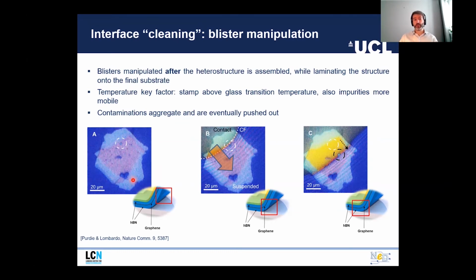And this is not on a substrate, it's on a polymeric stamp. As we laminate the heterostructure onto the final substrate, we combine the effect of temperature, which affects, first of all, the stamp, which is a polycarbonate stamp. When we bring the stamp above the glass transition temperature, it starts to become fluid. That factor combined with a gentle push on the side allows us to have a contact front that moves along the heterostructure.